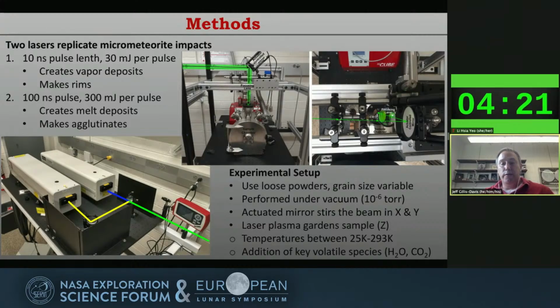And we also use loose powders to more faithfully replicate a lunar surface. And that actuated mirror steers the beam in X and Y. And the laser plasma actually gardens the sample. With each shot, it creates little craters. And in the future, those open circles, we're going to be adding temperature controls as well as the addition of volatile species.